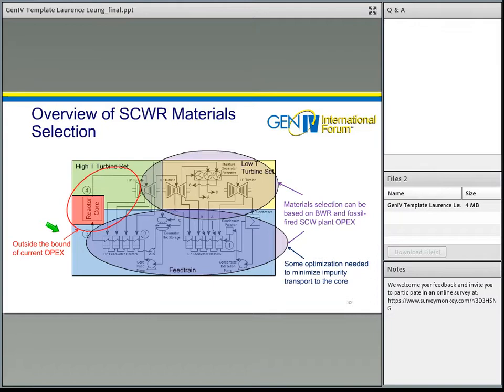So the focus is actually on the core and the high temperature turbine area, because that's the area outside the bounds of current operating experience. We need to focus on those areas to develop and establish a material candidate. We use different methodologies to rank the different materials for cladding. We look at five different materials: alloy 800H, stainless steel 310S, 625, 347, and 210, and look at properties, for example corrosion, oxide thickness, creep, ductility and strain. So we establish the differences in these properties.